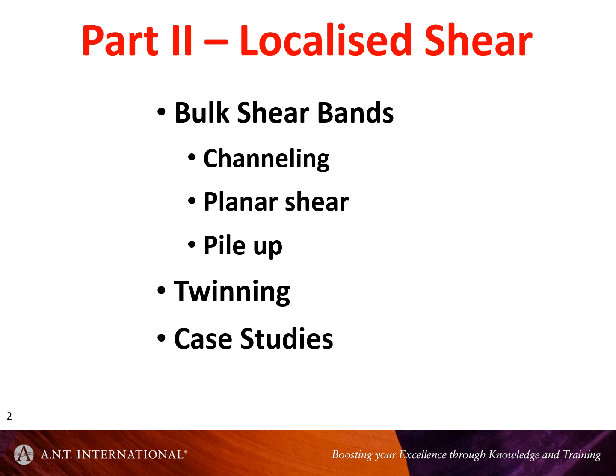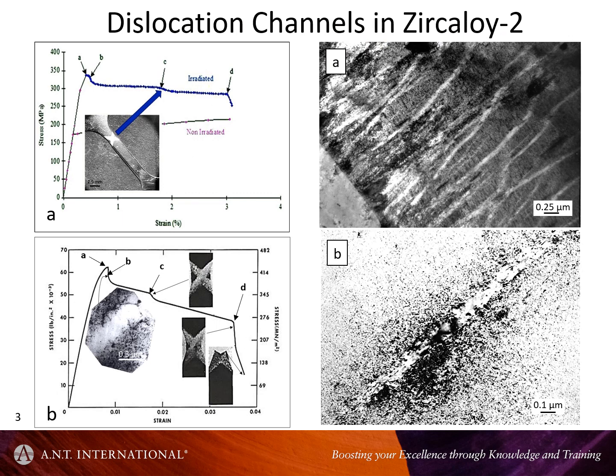So one of the things that's quite apart from the confusion between what is channeling and what is planar shear, there's confusion then with identification of channels in the TEM and basically the interpretation of images in terms of channeling when potentially they should really be interpreted as twins. And that's just a question of doing more detailed TEM analysis than some people might conduct. So let's get into it. We'll start by giving some examples of what we mean by channeling.